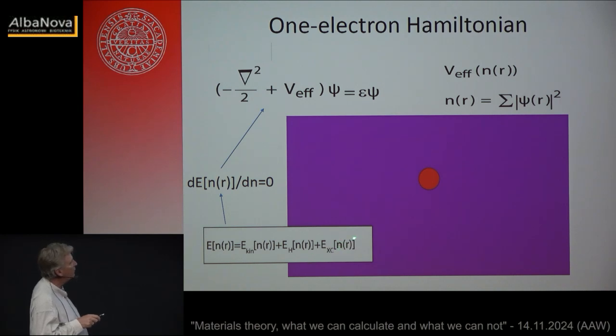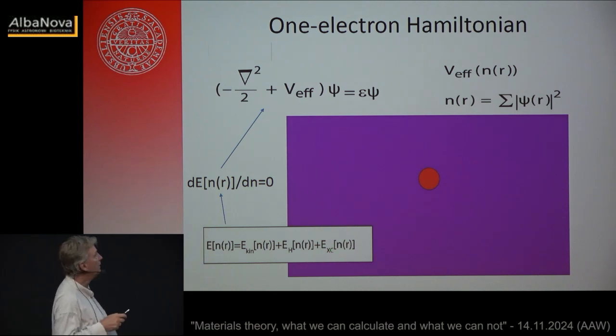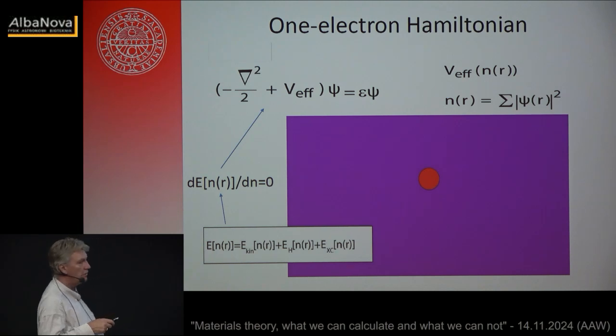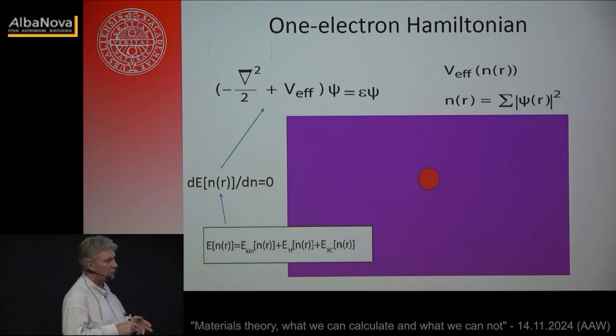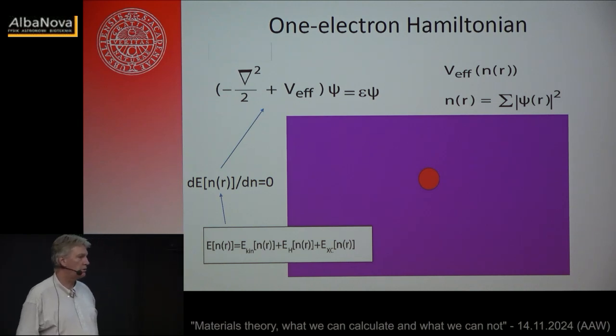But the penalty of having a lot of exchange splitting is that the kinetic energy is increased. So there's always a balance between the kinetic energy, electrons like to hop around on a lattice, versus being spin polarized. If I go through all the elements in the periodic system, all 300 functionals, all 300 effective potentials, all 300 versions of the exchange correlation energy, they would faithfully reproduce that iron, cobalt, and nickel should be spin polarized, whereas the ones that don't should not be. So that actually comes out okay. So the exchange energy is obtained. It's in here. Exactly.